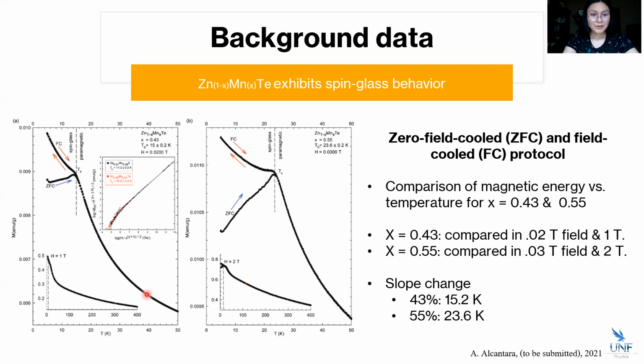So it follows this paramagnetic behavior as expected up until a certain temperature. And after this temperature, there is a cusp that occurs, and this cusp is caused by the system having to overcome a specific amount of energy to transition into the spin glass. And this is quite indicative of a spin glass, and it's shown here in this log-log plot, where you can see a previously known spin glass plotted in black and the change in slope that it has here. And then in the red is the zinc manganese telluride, where you can see that it follows almost the same exact slope.